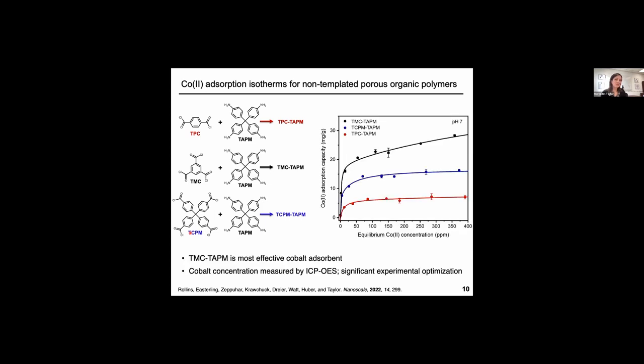We tested whether they would be able to capture cobalt ions from aqueous solution. And in fact, they're all kind of decent. Like, in comparison to other materials that people are publishing on for cobalt capture, these porous polymers performed okay at pulling cobalt out of water. The one that happened to have the highest cobalt adsorption capacity is the one shown here in black. You take a triacyl chloride and react it with this tetraamine, and you obtain a material that is able to pull a decent amount of cobalt ions out of water. So this was the material that we went with to then try out that ion templating strategy.